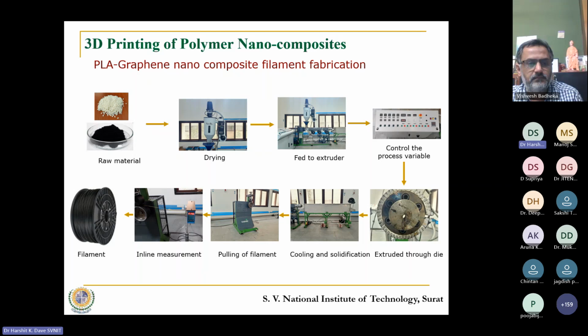We also have attempted creating PLA graphene nanocomposite filament by using our lab scale single screw extruder system, wherein we mixed the graphene with PLA granules in different proportions, say 1, 3, and 5%, I suppose. And the advantage of nanoparticles like graphene and CNT is that, in spite of being utilized in a very small proportion, they provide very large surface area, because of which they cover the granules very well. And so when they are extruded, they come up with a good quality of filament.